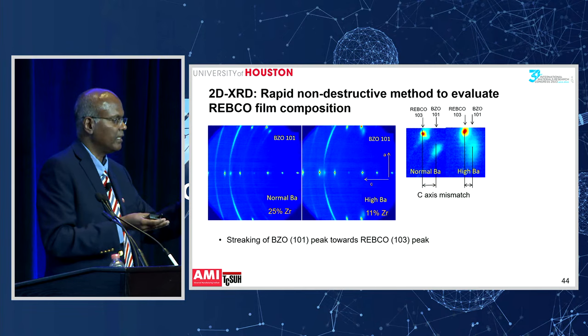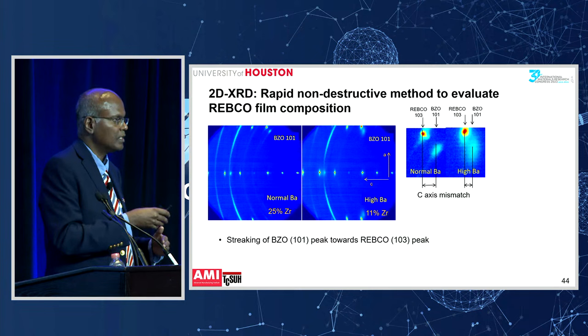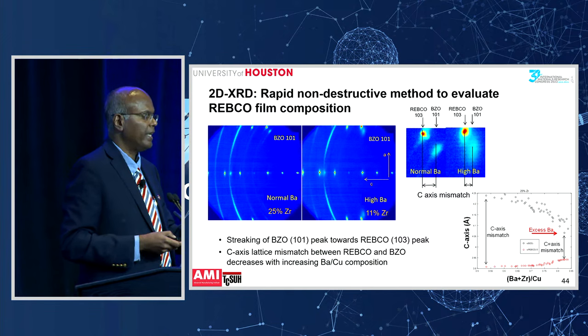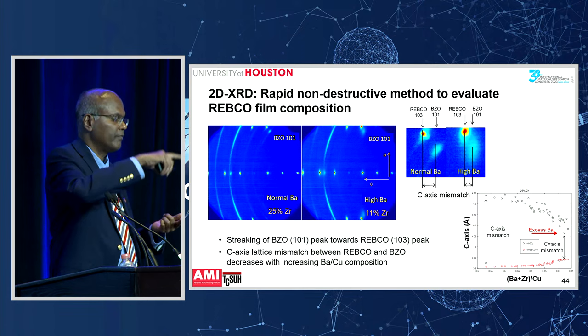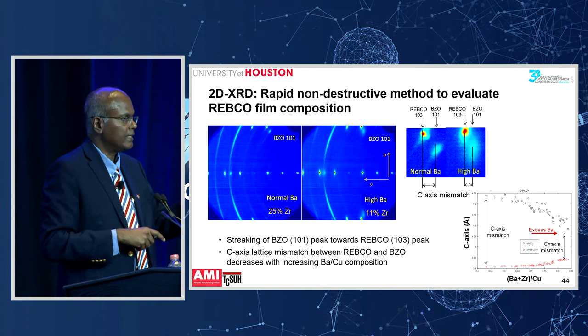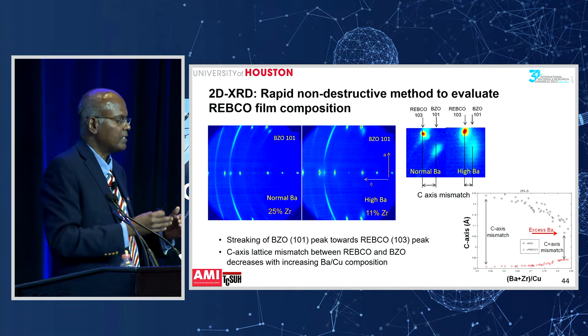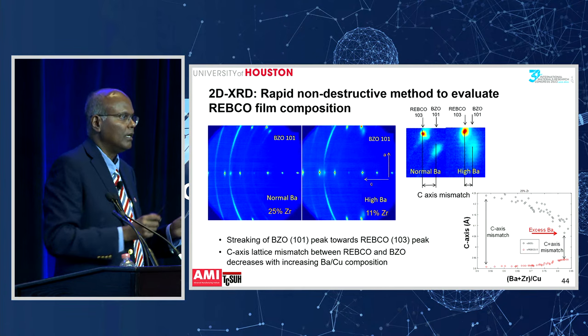Whereas when you have a high barium, which is what you're interested in, you can see the peaks are getting closer together. The reason is quite simple: when you add barium, as I already mentioned, the c-axis parameter of the superconductor film increases, which is what you see at the bottom in the red circles. Simultaneously, the c-axis lattice parameter of the barium zirconate decreases. So as you increase the barium, the two lattices get closer to each other, and that's why the peaks are getting closer to each other, or the angle between them is smaller.